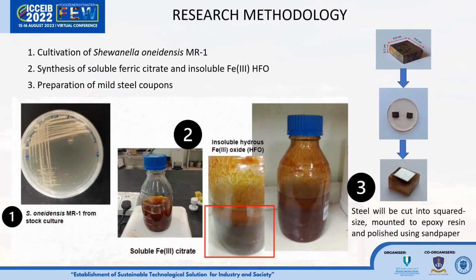Now we proceed to the methodology part. We worked mainly on three main stages. The first stage was cultivation of Shewanella oneidensis MR-1 in Luria Bertani broth with agitation speed of 150 rpm at 30 degrees Celsius overnight.